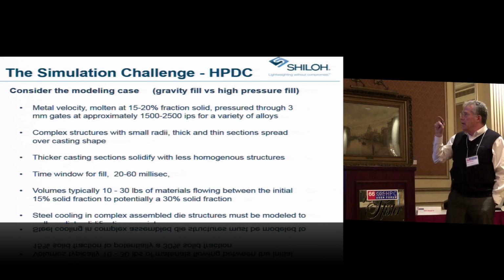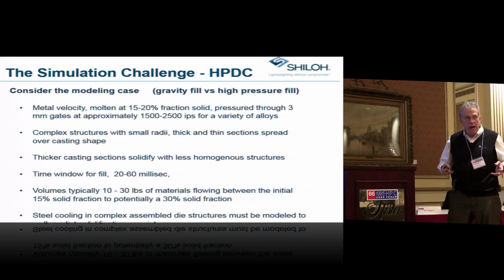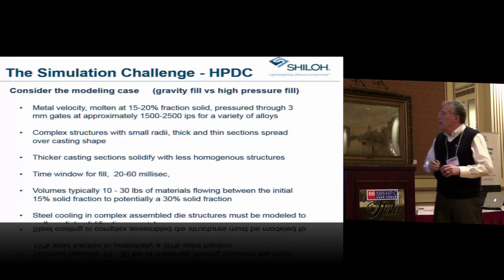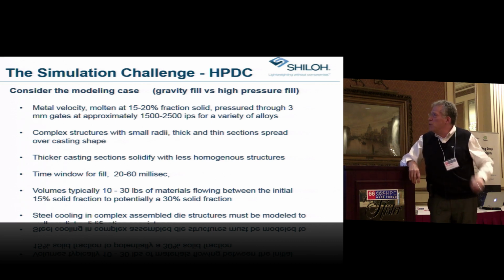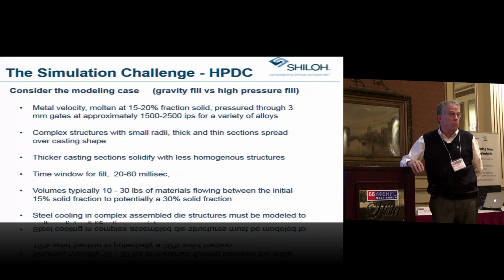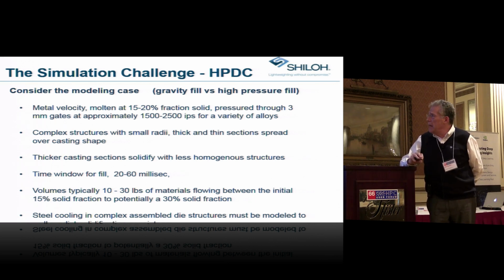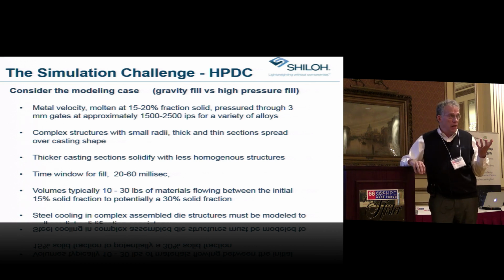So if you consider the modeling case, we've got this metal velocity that's moving. Maybe it's got a 15 or a 20% fraction solid, so the viscosity is something you can predict within a range. It's typically pressured through a 3 millimeter gate, so you have a kind of atomization spray at maybe between 1500 and 2,500 inches per second fill speed. Complex structures, very small radius, so you can imagine the modeling challenge of having 2 millimeter, 3 millimeter radiuses and corners and trying to see how that structure is going to fill.